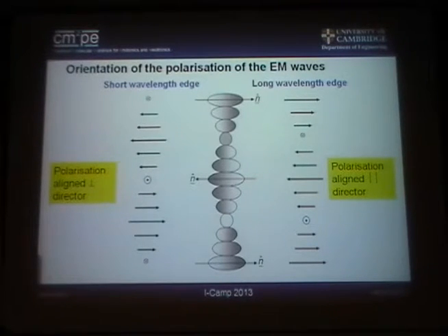Because of the dye guest-host effect, the dye molecules tend to align preferentially with the director, and so you get more coupling into the long wavelength edge than you do to the short wavelength edge. And if you incorporate the fact that when you have losses as well, the long wavelength edge is the dominant mode, this is why all the work that we've done has really focused just on long wavelength edge, photonic band edge lasing.